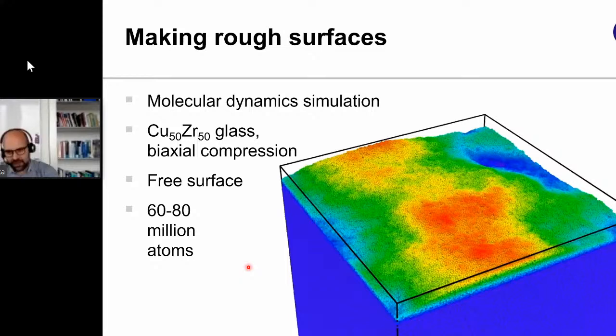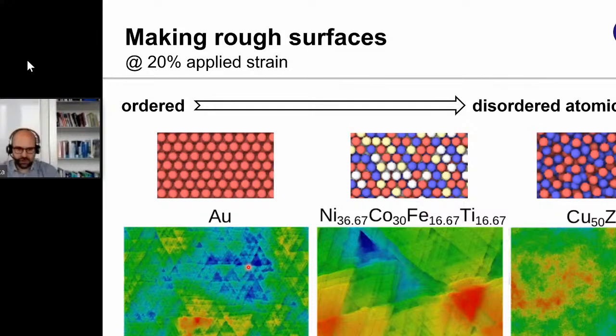Now, I said the glass is homogeneous, but really at atomic scales there is glassy heterogeneity. So we did these calculations for three different types of systems: single crystalline gold, these are 111 surfaces, a high entropy alloy, and this copper zirconium glass. These systems represent different limits: perfectly ordered in the case of single crystalline gold, where each atom sits next to each other; then stoichiometric disorder in this high entropy alloy, an FCC lattice but with random elements, nickel, cobalt, iron, and titanium, with the composition shown down here; and of course this glassy material that has disorder at the atomic scale. And all of these develop surface roughness.